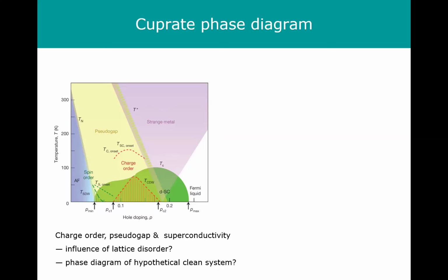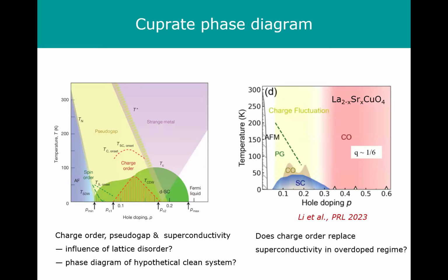For this particular material system, we were also motivated by this paper here, which claimed that the end of the superconducting dome coincides with the onset of a new charge-ordered phase with an unconventional wave vector, 1/6 the Brillouin zone. So the question then is, is perhaps the onset of charge order responsible for the disappearance of superconductivity rather than disorder?